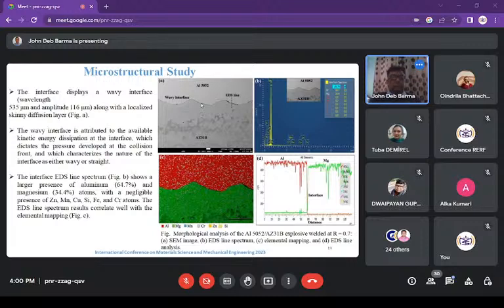Now the interface, if we talk about the EDS line spectrum, figure B, it shows a larger presence of aluminum, as you can see here, as well as magnesium also. Here, if we talk about the percentages, aluminum, as you can see, is around 64.7%, magnesium is 34.4%, with a negligible presence of zinc, manganese, copper, silicon, iron, chromium atoms. And the EDS line spectrum results correlate well with the elemental mapping that you can see here in this figure.